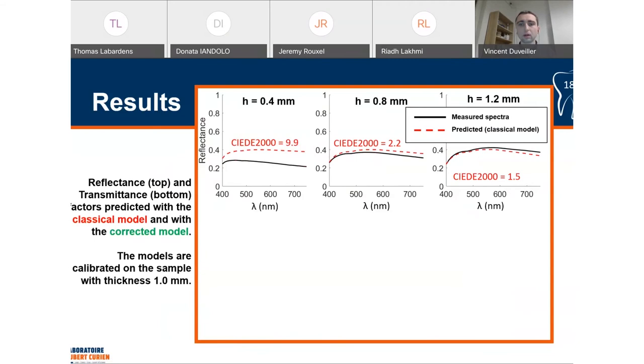For 0.8 millimeter, the prediction is better, but 2.2 units is still above the acceptability threshold of 2 units. So this prediction is not good either. For 1.2 millimeter, the color distance between the prediction and the measurement is 1.5 units. So it's below the acceptability threshold, but still above the perceptibility threshold. So it's not a great prediction tool.